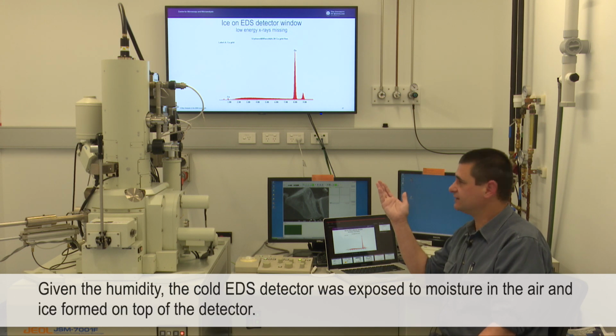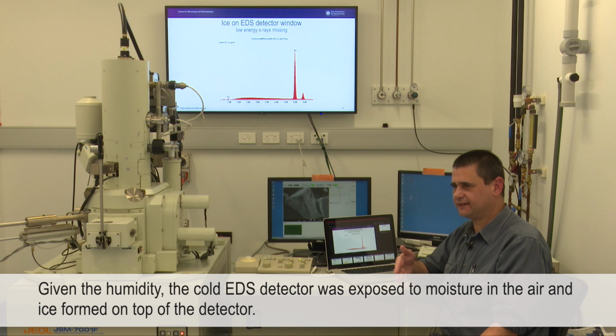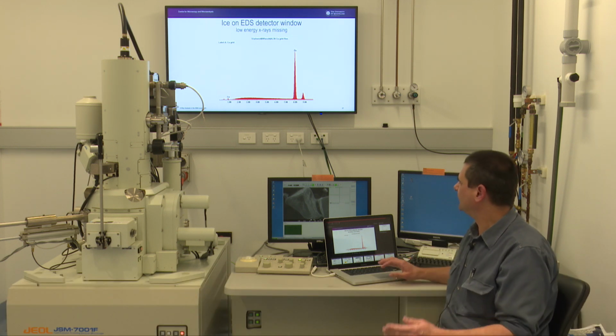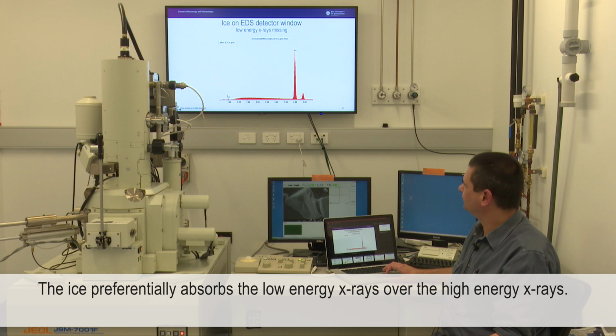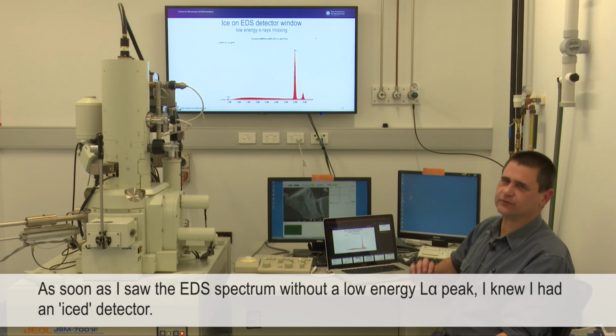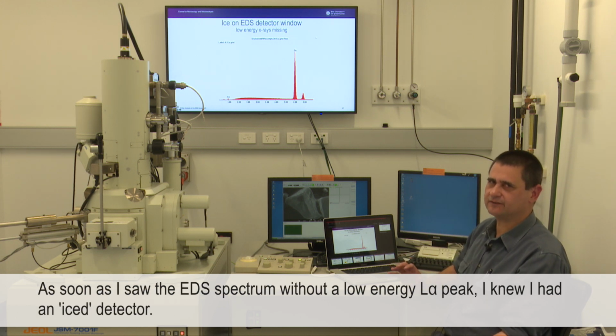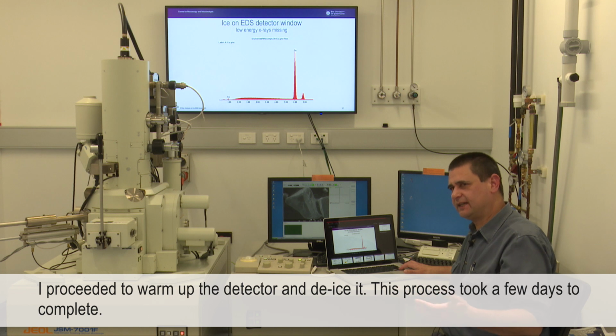Given the humidity, that cold EDS detector was exposed to moisture in the air and ice formed on top of the detector. Not enough that you could see it with your eye, but enough that the ice preferentially absorbs the low energy X-rays over the high energy X-rays. As soon as I saw that, I knew I had an iced detector.